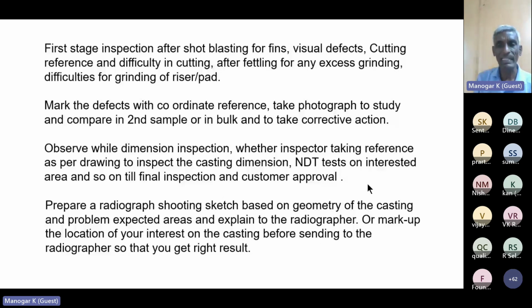And observing the NDT results, especially in RT, before you send the casting for radiography, you should make the casting thoroughly inspected. Any visual repair should be repaired and take a note of the defects, and then send the casting for RT. Sometimes what happens, people for urgency send the casting without seeing. Then these visual defects are seen on the RT, then they are unnecessarily repairing and taking action for that without knowing this is a visual defect.